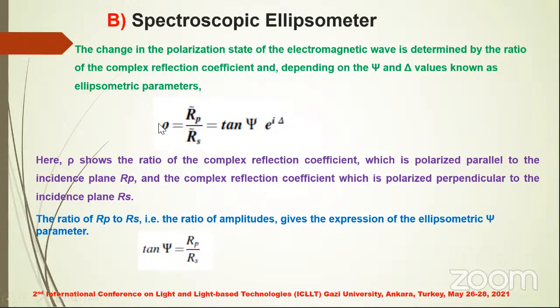Rho equals Rp divided by Rs equals tangent psi e to the i delta. Here rho shows the ratio of the complex reflection coefficient which is polarized parallel to the plane of incidence, Rp, and the complex reflection coefficient perpendicular to it, Rs. The ratio of the amplitudes gives the expression of the ellipsometric psi parameter: tangent psi equals the magnitude of Rp divided by Rs. The phase difference between Rp and Rs gives another ellipsometric parameter, delta.